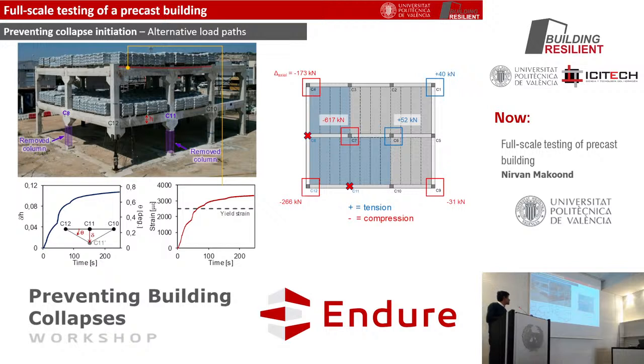And here we summarize the results. As we can see, the displacement was very small, still significantly lower than the depth of the beam, so not sufficient to activate catenary action, even with such a high magnitude of loading. There was fairly limited damage to reinforcement, with just some of the continuity reinforcement in the top beams just about yielding. And here I've shown the redistribution of loads to the adjacent columns, which allowed us to see a bit how the alternative load paths were developed experimentally.